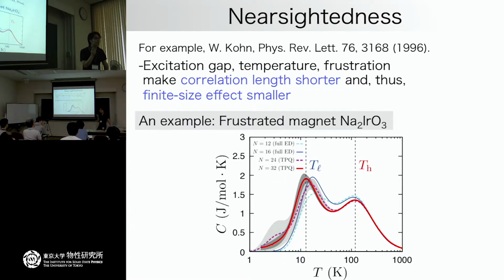But my point is that please compare with the peak temperature of the heat capacity. Just comparing the scale with the coupling is not so important, because if you change the lattice structure and if you change the system, then it's not so useful. Please compare the temperature dependence of the entropy. We should have some independent temperature scale relevant to each system. Here, the relevant temperature scale is this one, and compared with this temperature, we should discuss the behavior. So if we compare with the Kagome lattice, then we should pin down the temperature scale in the Kagome lattice. In this sense, the 0.1 J is around here, but here we still have a peak structure below this, and we keep the large entropy. But the problem is at which temperature the heat capacity peak appears in the Kagome lattice. And this is a really important point.